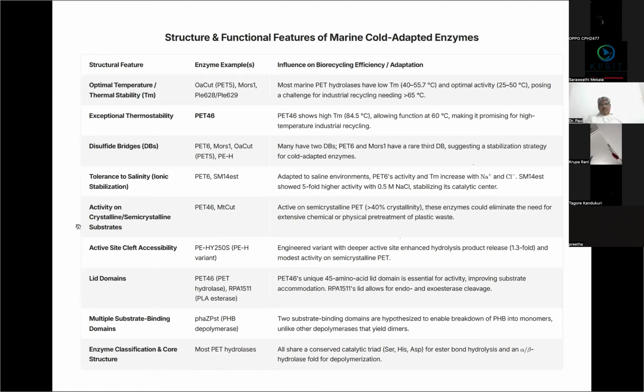Some of the structural features of these marine cold adapted PETases is they have an optimal temperature at 0 to 20, but there are certain exceptions. Some marine organisms have PETases which have activity at higher temperatures also. For example, PET46 shows a high Tm of 84.5 degrees centigrade, allowing function at 60 degrees, making it promising for high temperature industrial recycling.